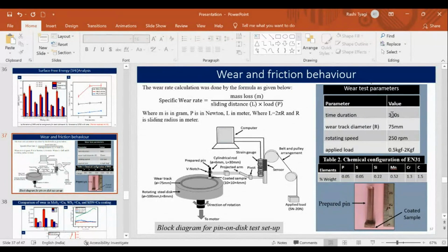This is the time duration for which the wear test is performed: 300 seconds. The rotating speed of the disc that we have used is 250 rpm. The load that is applied is 0.5 kgf to 2 kgf. By applying this load and using this setup, we obtain the graph in the computer, because there is a belt pulley arrangement and a sensor that gives you how much wear takes place from this coating. The strain gauge gives the command to the sensor, then the sensor analyzes how much wear has been removed and gives the information to the computer. Then you can see how much wear there is in this process.